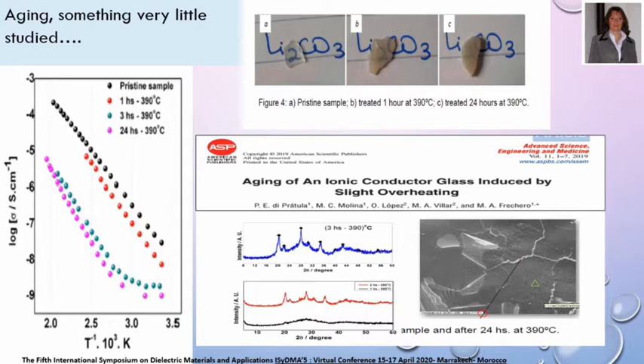Then, considering how promising is this glass as electrolyte, we studied its aging. Aging is something that needs more attention because many times great materials don't resist along the time and cycles in batteries. We put our glass through different overheating processes near to its glass transition temperature, and we analyzed how reliable its structure was, how it affected its conductivity through these periods of overheating.